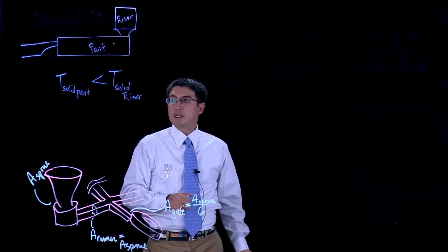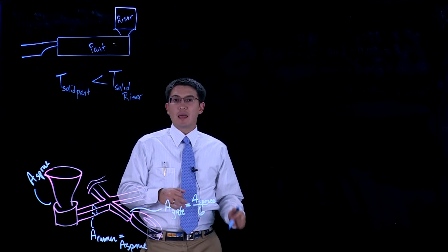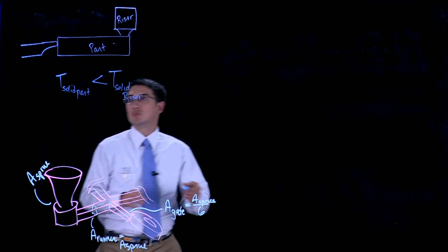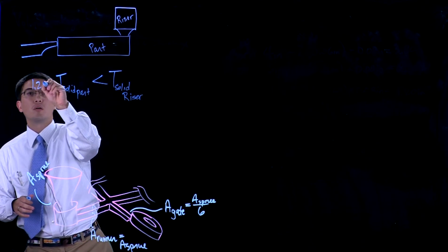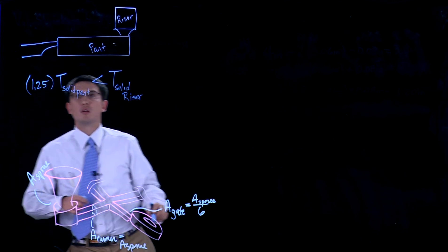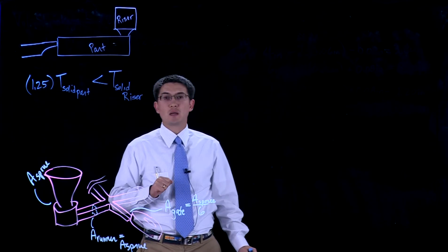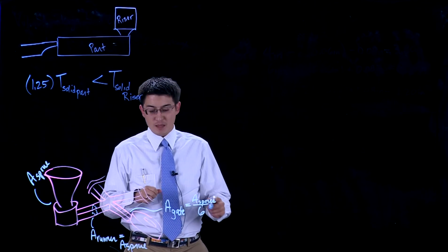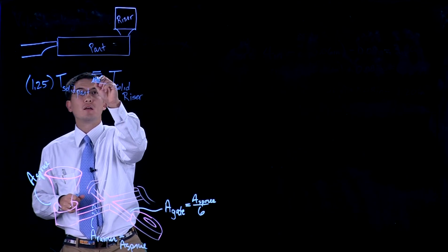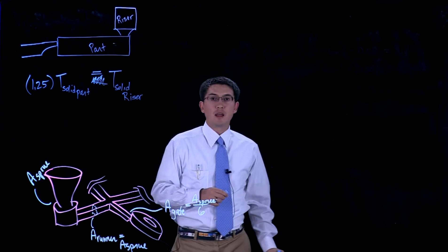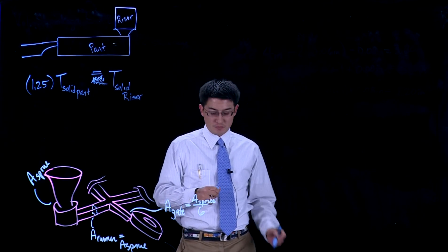Specifically in the problem statement, it says at least 25% more time. So you add on an additional 25% of time for your solidification time of the part, and that's how much time we want your riser solidification time to equal.